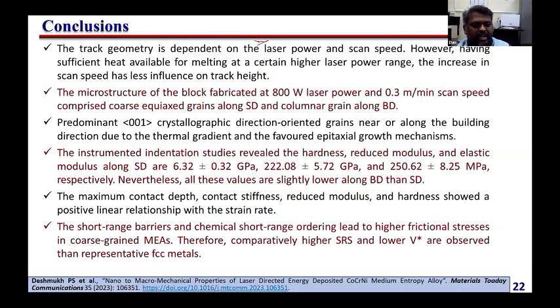Okay. So also we did some nanoindentation. So we got this strain rate sensitivity and lower activation volume. The reason is mainly due to short range barriers, right? So that's what I told. So this is from the first study we got.